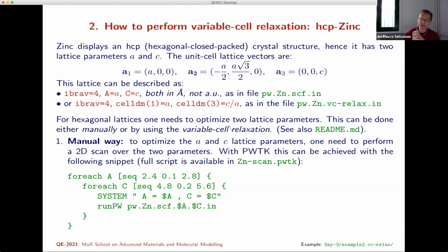And usually, in most of these cases, we are using a GGA, as has maybe been seen already. Usually we are more or less 1% larger than the experimental lattice constant. And I would say 1% is not too bad. That's the value which traditionally one would use. There are cases when one actually uses the experimental lattice constant for real calculation applications.